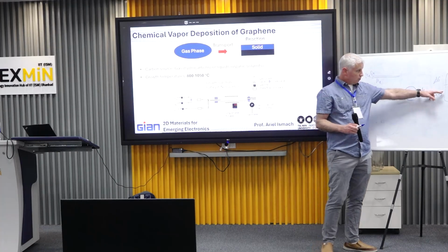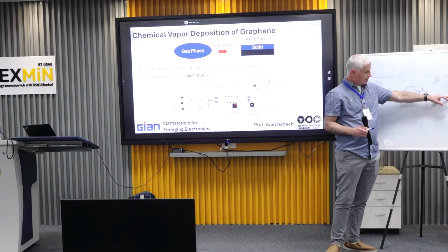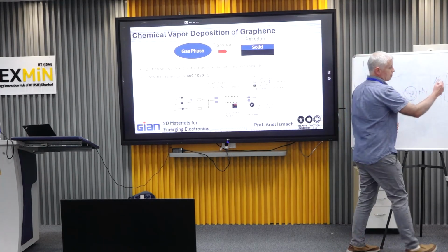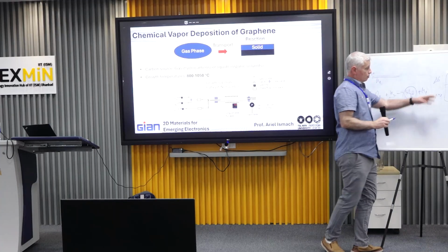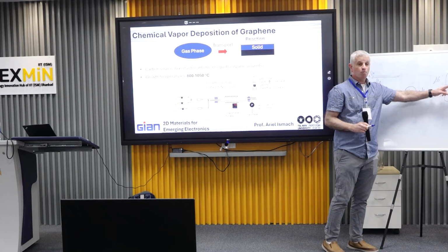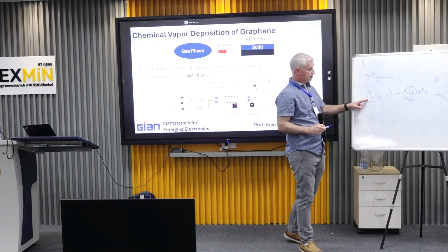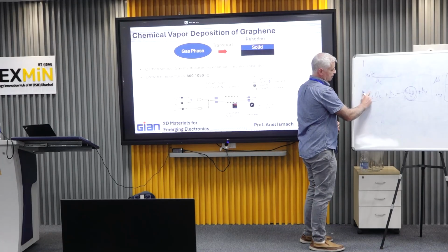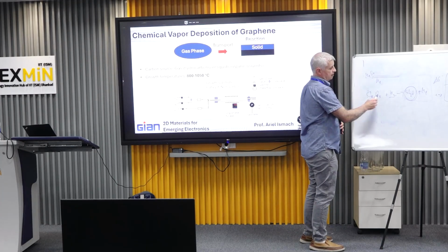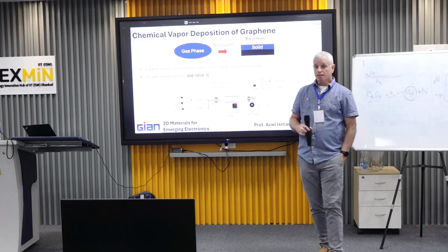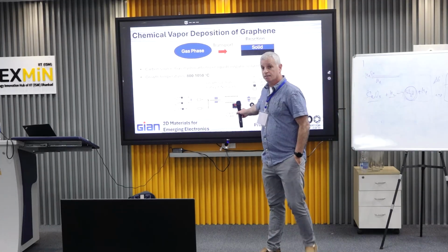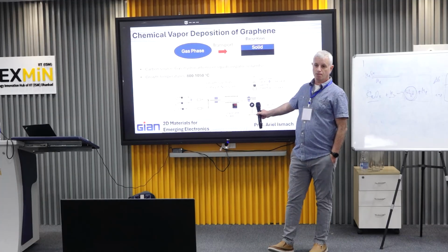So if so, like in this case, and this is the case for copper oxide and also nickel oxide, then we can run the system, in this case with copper oxide, and reduce it in situ in the system before the growth.